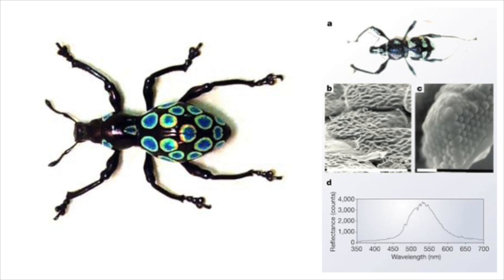Scanning electron microscopy reveals that the internal particles are arranged in flat layers with a precise hexagonal close-packed order. When the lattice constant of this crystal approaches half the wavelength of visible light, the structure acts as a three-dimensional diffraction grating, forming optical domains within a single scale. This nanostructure is the most common packing arrangement found in opal, although opal microspheres may occasionally adopt face-centered cubic packing, and it enables the reflection of a narrow range of wavelengths over a wide range of incident angles.